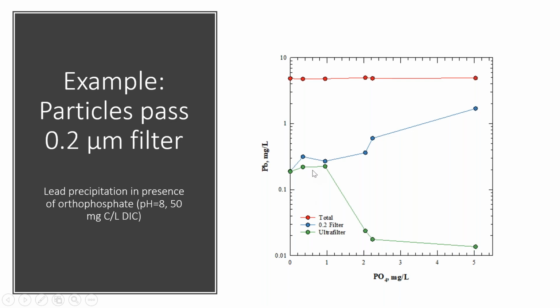So you'd walk away from this saying, my particles are all pretty big. They're coming out with the 0.2 micron filter, so they must be bigger than that. But if you remember that picture of the two different particle sizes, the small lead phosphate particles and the big lead carbonate particles, that's what's happening here. If you look at the ultrafilter and see what's precipitated on the surface of that, you're going to find a mix of those two solids.